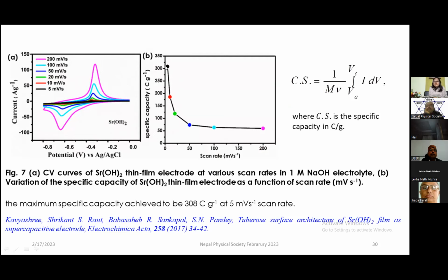The specific capacity comes out to be more than 300, it is 308 coulomb per gram at 5 millivolt per second scan rate. If you increase the scan rate, the specific capacity decreases. A low scan rate means the electrolyte gets more time to interact with the electrode.